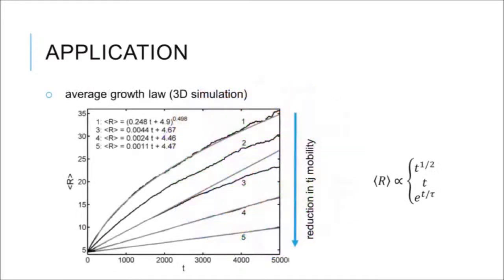Let's plot the average growth law, the average grain radius as a function of annealing time. The upper curve is normal grain growth, and as we systematically reduce the triple junction mobility, we reach a point where for long annealing times we observe a linear relation between average radius and annealing time, just as predicted analytically for triple junction mobility.